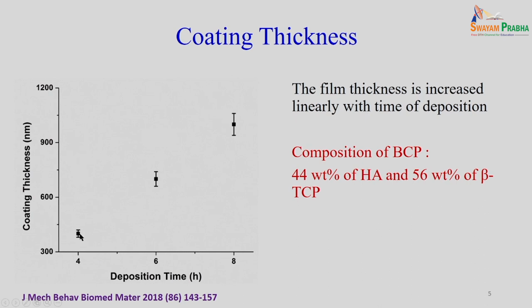It was 400 nanometer at 4 hours, 700 nanometer at 6 hours, and at 8 hours we got about 1100 nanometer thickness.